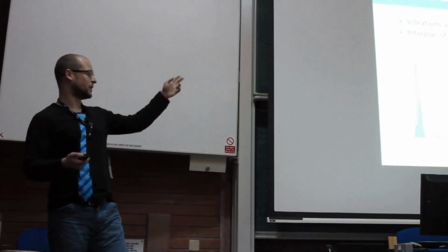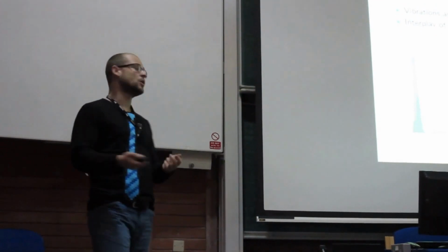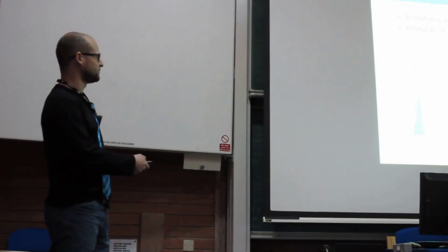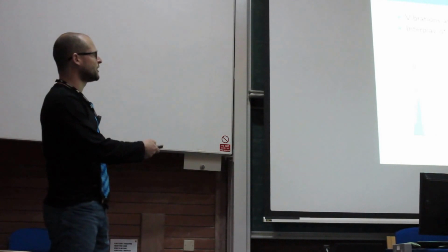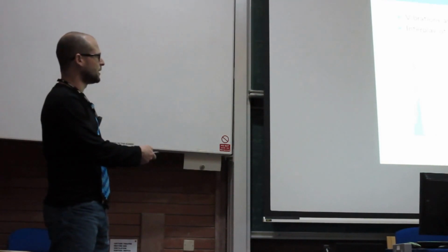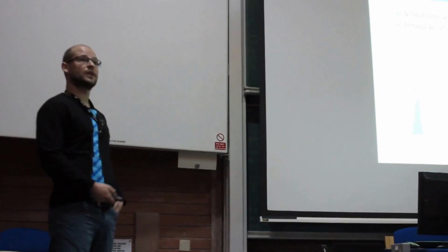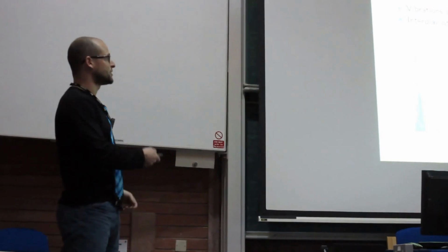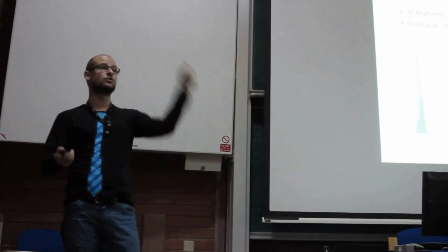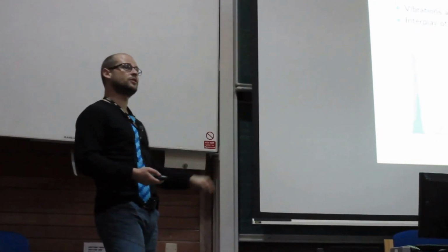For example, you can assign the symmetry of each mode, or you can project the vibration onto the different parts of the structure. In this first panel, I show you the vibration related to the central molecule, which is the greenish color, and the vibration of the cage. At the beginning, we thought the two parts were not connected, but actually we found there is a coupling, there is an overlap between the vibrations. That's very important because if you change the molecule and keep the cage the same, you can change the vibration, you can change the spectra, and you can detect new material in this way.